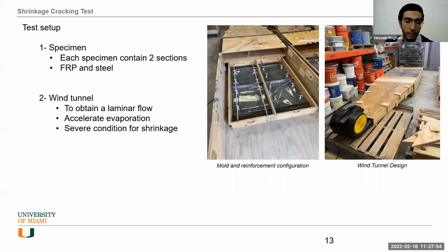Here's the test setup. In the pictures, you can see our setup in the same slab. On one side, we have the FRP, and on the other side is the conventional steel. And the wind tunnel in the photos on the right helps us make a laminar airflow on the surface of the concrete to accelerate the evaporation rate of water, which is critical in plastic shrinkage, and make the conditions severe enough for cracking.